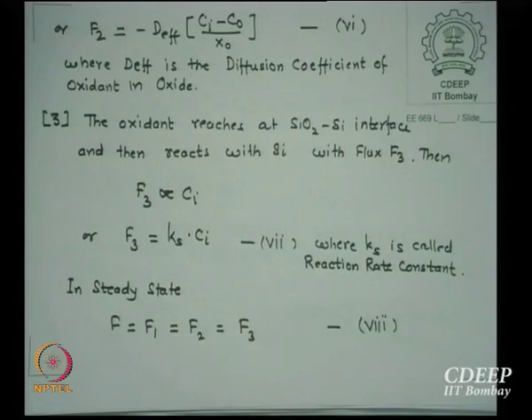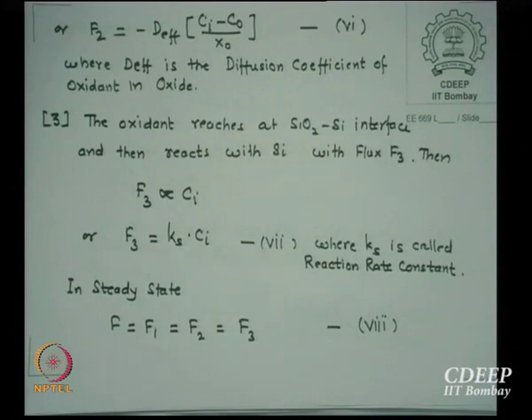So if I write that, F2 is minus D effective, minus because I am subtracting, (Ci minus C0) by X0. Why did I do this? Because final concentration minus the initial concentration divided by X is actually the slope. It is essentially how we define that, it is going down. So that final concentration minus the initial concentration divided by X0 is the gradient. So F2 is minus D effective times (Ci minus C0) by X0, where D effective is the diffusion coefficient of oxidant in oxide. This is flux F2. Now this is made available to react with silicon.